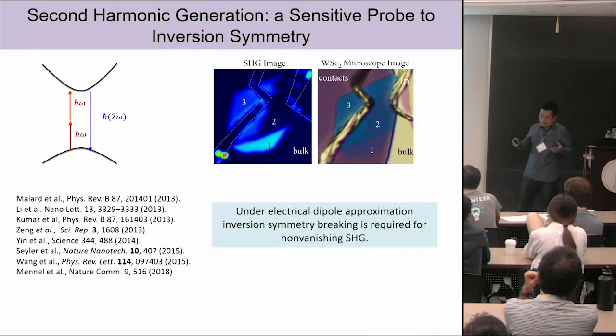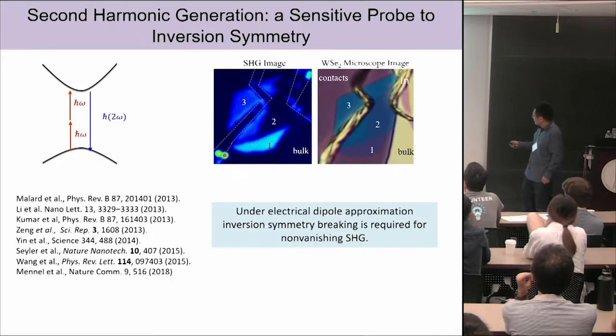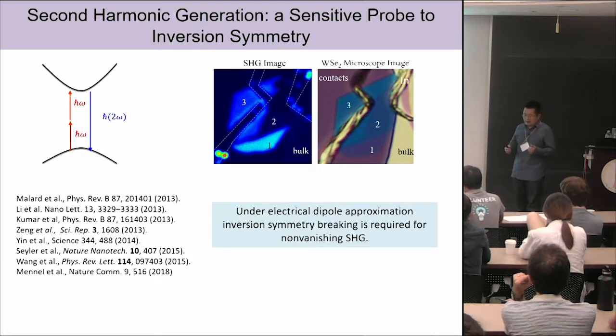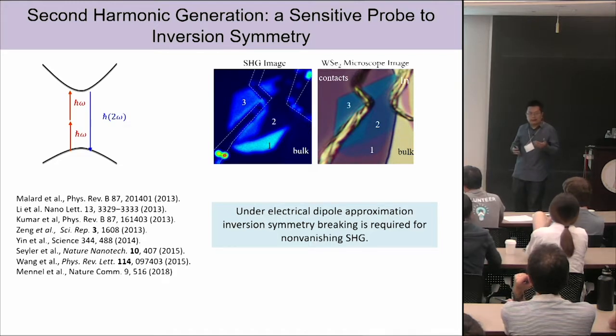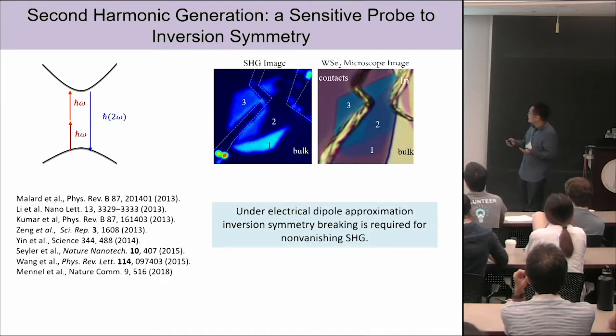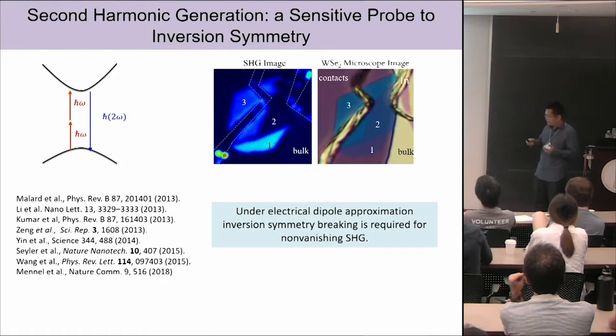To identify this, we use second harmonic generation measurements. The key message for second harmonic generation is that it's very sensitive to crystal symmetries, because in order to get second harmonic generation, under the electric dipole approximation, the inversion symmetry must be broken.